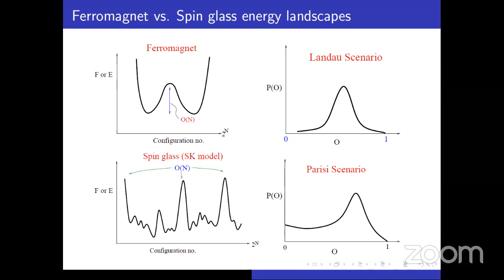As you can see in the lower left panel, free energy versus the configuration number for N spins, there are 2 to the N configurations. So in the configuration space, it looks like this. Of course, there is a symmetric part as in the upper one, but I have not drawn that. Since it is non-ergodic, each portion of the landscape has its own order parameter, and that distribution will look like this in the thermodynamic limit, N going to infinity. So it is not going to become a delta function as in the Landau case. Now I'm showing the second slide, ferromagnetic versus spin glass energy landscape.